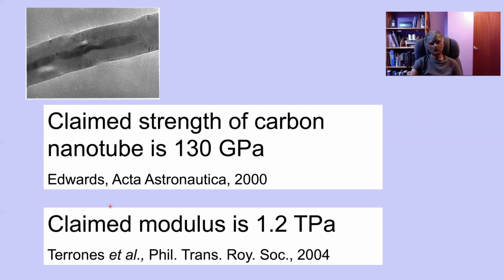The reason why this was reported in Acta Astronautica is that the idea was to build a space elevator with a carbon nanotube rope that is 100,000 kilometers long. And because it would be light compared with any other material that we know, it could support its own weight. Whereas, if you try to make it out of steel, that would not be possible. And it also has a modulus along its length, which is roughly 6 times that of steel. So that's very good for a rope.